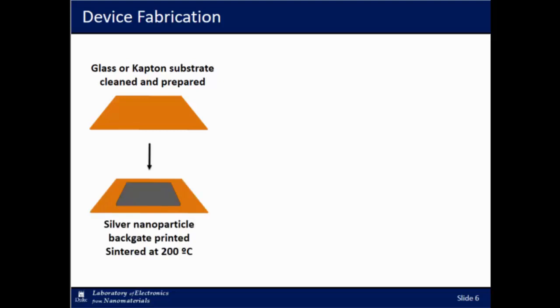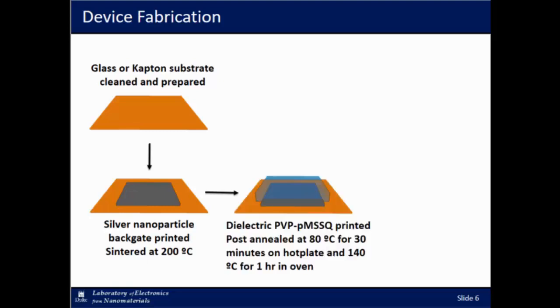And these are backgated transistor devices. So first we need a conducting backgate. And for that, we use silver nanoparticle ink. These are particles about the size of 30 to 50 nanometers. And we print them and then we sinter at 200 degrees C. And what that does is it merges the nanoparticles to form a continuous conducting film.